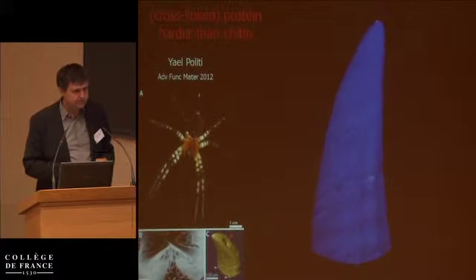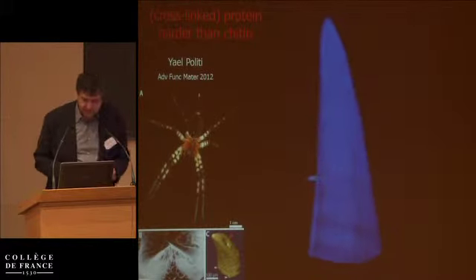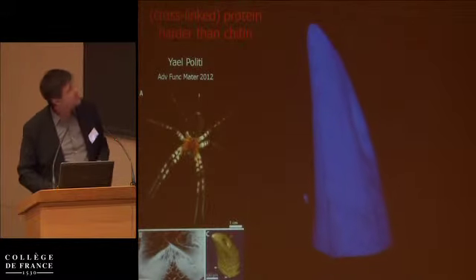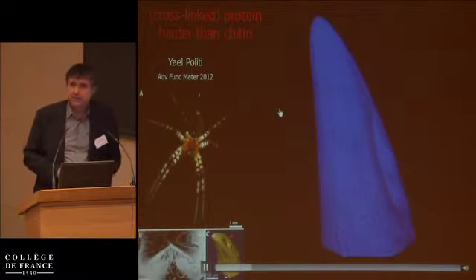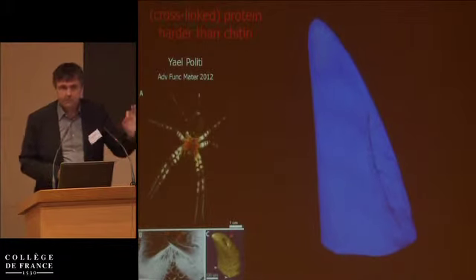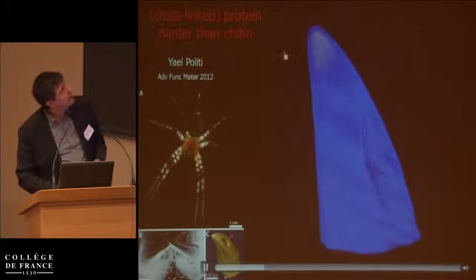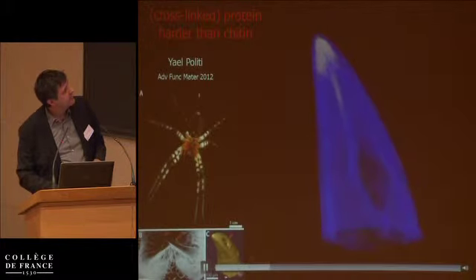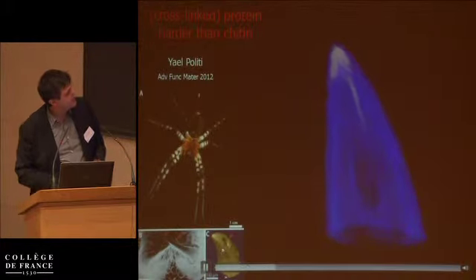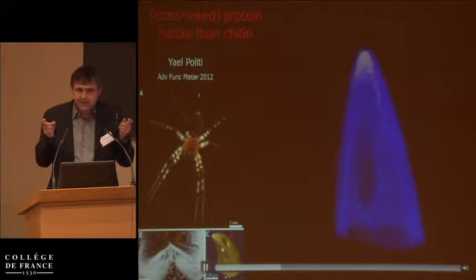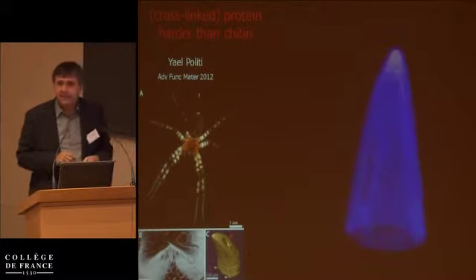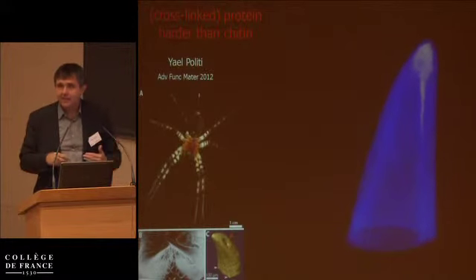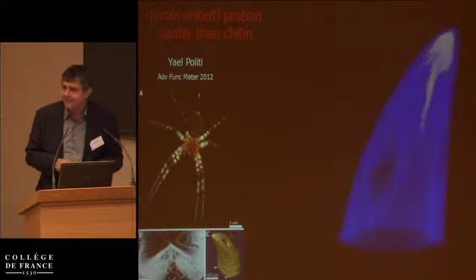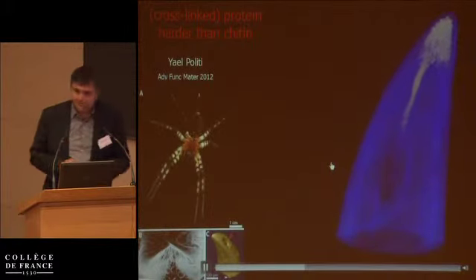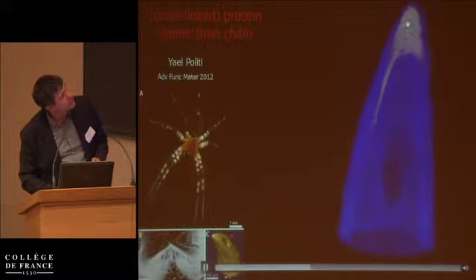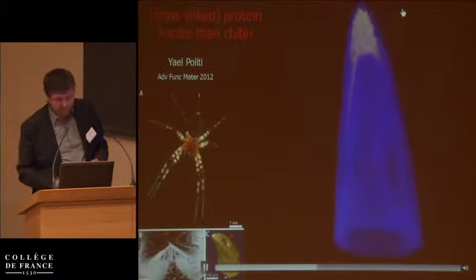and this is just to make the point that these metal coordination bonds are really very interesting strategies. In fact, it turns out that just by cross-linking, you can make a protein harder than chitin, just by these cross-links. And one example is here. This is a spider, and this is just the device that the spider uses to inject the venom. It's made of chitin, and the prey has a carapace made of chitin. So how do you make protein harder than chitin? Well, the trick is you don't use chitin, you put actually protein in the tip, and the tip of this chitin needle is actually made of protein.